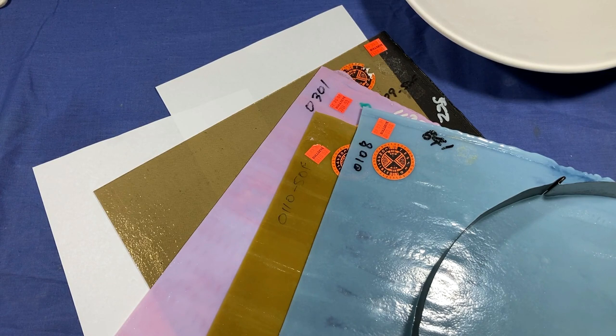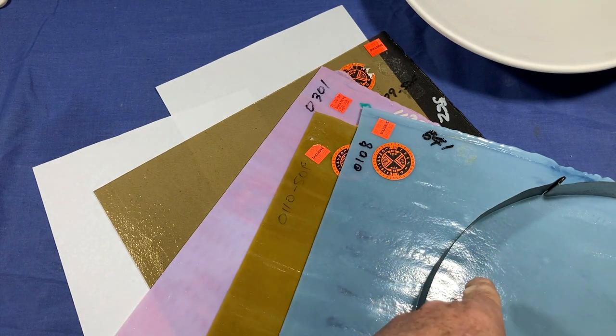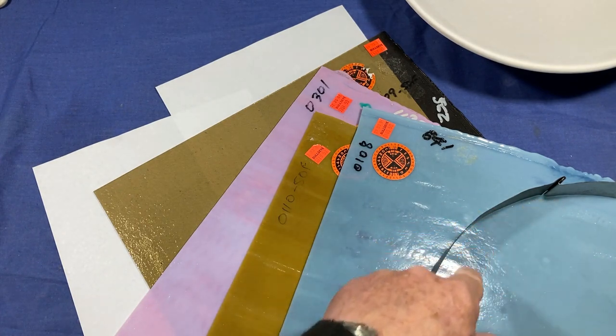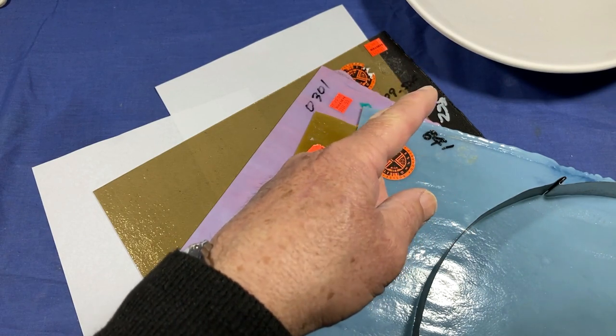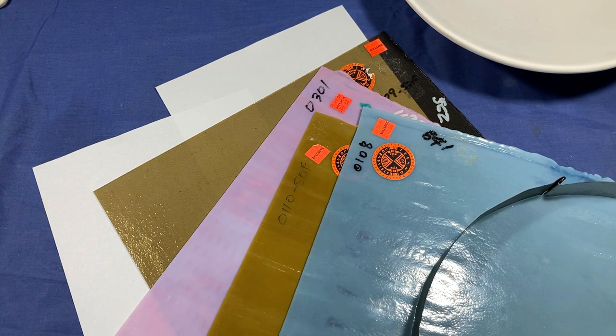If you haven't watched my channel before, I just need to let you know that all the glass I'm using is Bullseye 90 COE. And when we do the disc in this former, I'll be putting thinfire down, and lining the inside with a couple of mil of fiber paper. And in the mold, I'll be using boron nitride spray as a separator. So if you don't use 90 COE glass, just make sure you adjust any schedules I give you to match your COE and your kiln.